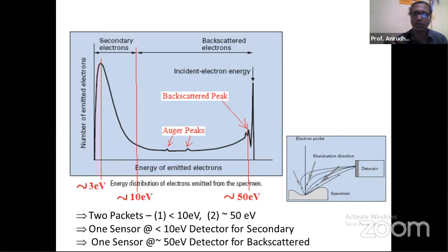So they would interact with this matter and in turn would eject electrons. So if we collect those electrons using a detector which is similar to what we mentioned in the case of XPS, then the energy distribution of these electrons emerging from the surface because of the impinging incident electron beam, if you plot it, this is how their energy distribution would look like. I'm not going into the details of it.